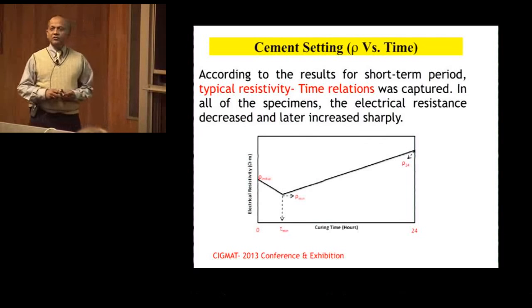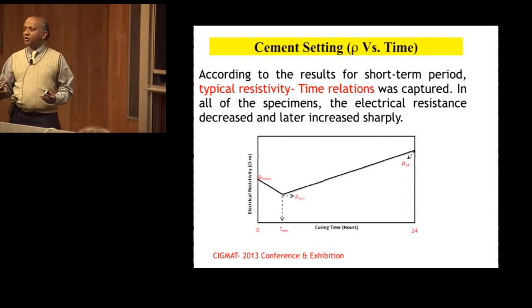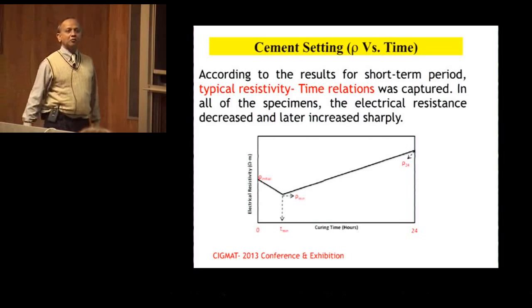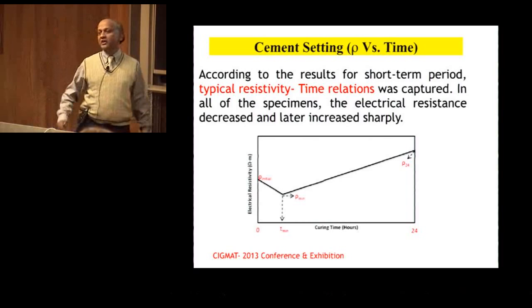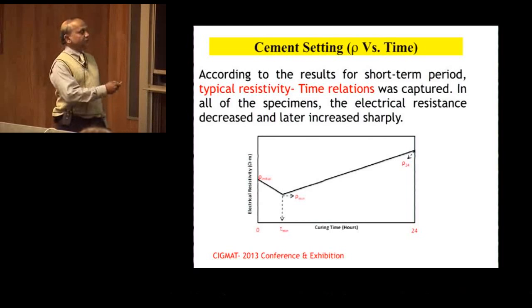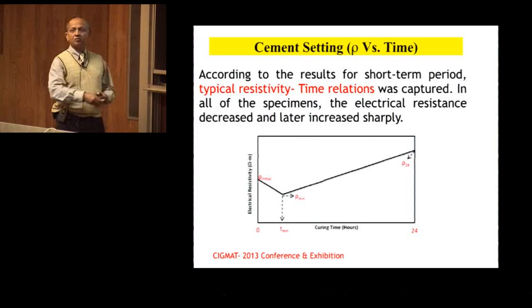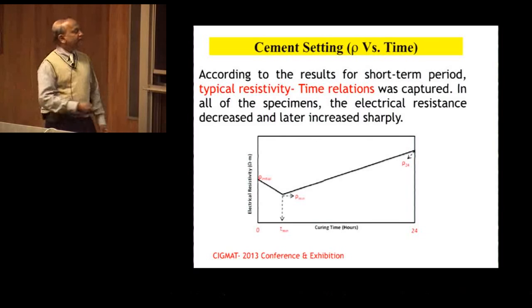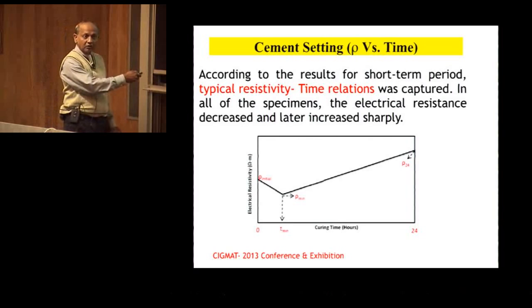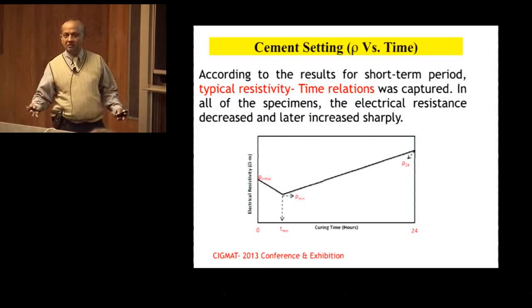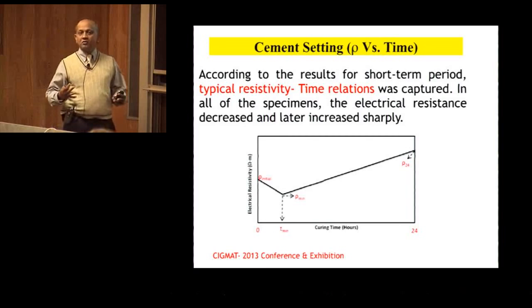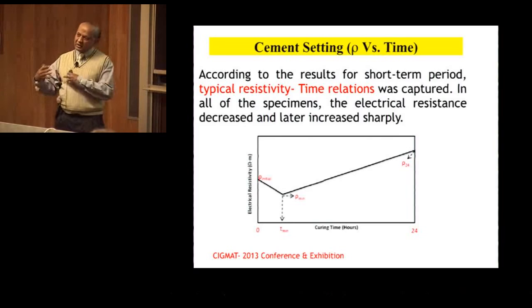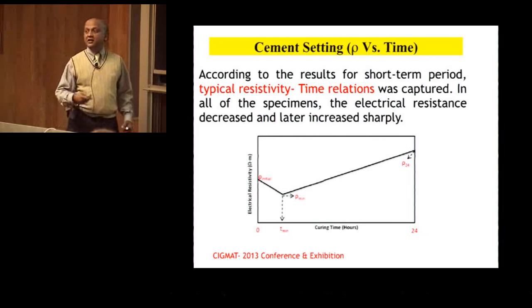So now, if resistivity is something to be monitored, are we just going after one number or are we going after a number of other factors? It turns out, for cement, the resistivity actually starts here when you mix it, and then it drops because there's a lot of chemical reaction going on. Then it reaches a minimum value, and then it keeps on increasing because of hydration of the cement. And this is already proven. What we are doing is quantifying it and making the material more sensing and coming up with parameters.